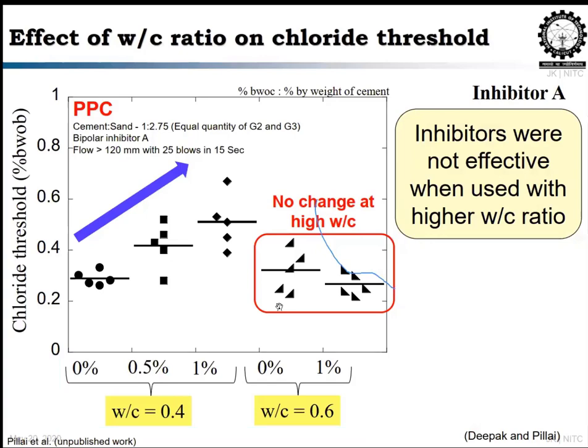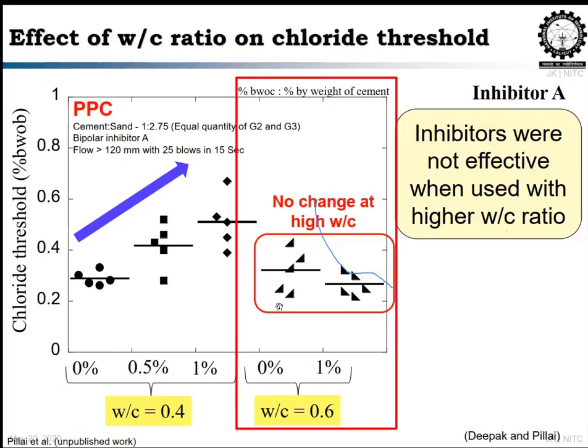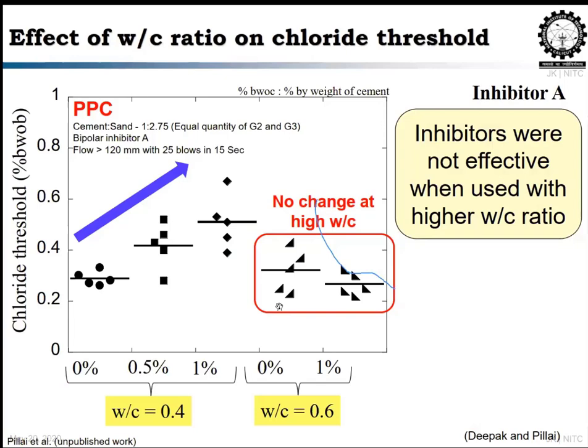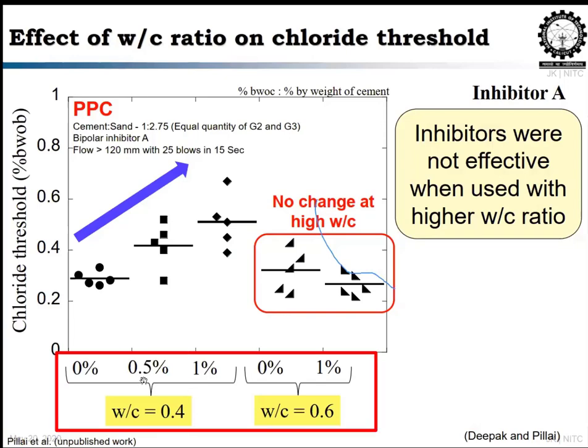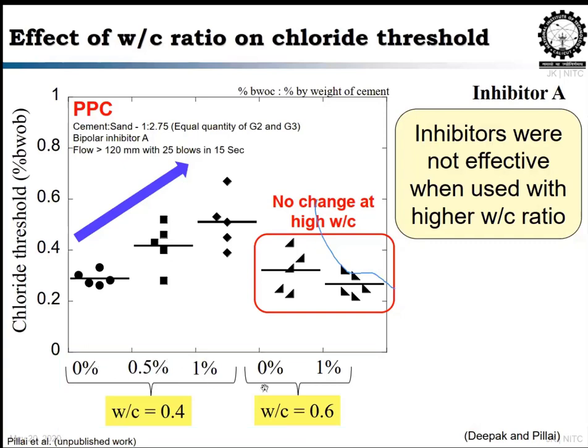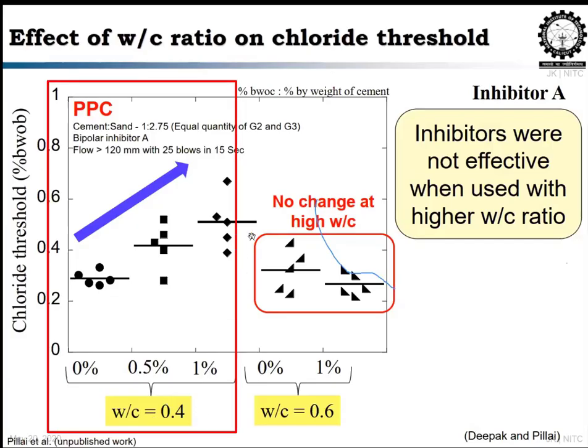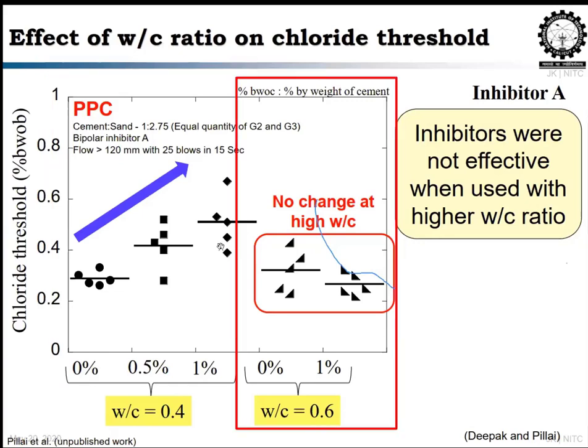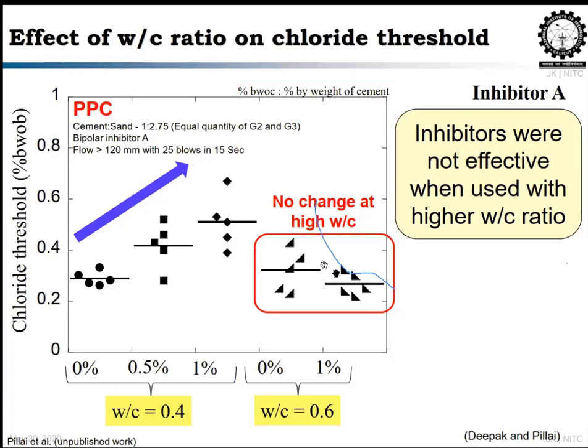For example, we tried a 0.4 water cement ratio and a 0.6 water cement ratio. With 0.4 we tried different dosages of inhibitor, 0, 0.5 and 1%, and with 0.6 we tried 0 and 1%. With the 0.4 water cement ratio, with the increase in dosage, you can see the increase in the threshold level. But with the water cement ratio of 0.6, with the increase in dosage, you couldn't get the expected threshold level. Why? Because these admixtures are diluted and lose their efficiency. That is the major problem.